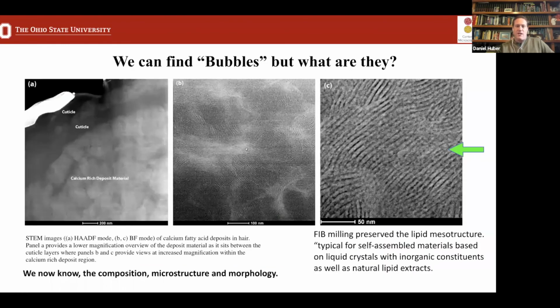There's definitely calcium there. If we zoom in even further with the HAADF STEM imaging, we can start to look at the internal structure of each one of those little blobs inside of that calcium-rich material. And what we see here in section C is the same structure, a 7 to 20 nanometer lattice repeat. This is typical of what's been seen in other self-assembled liquid crystals. This has actually been seen in natural lipids. So this is giving us a good indication that this is a calcium fatty acid.